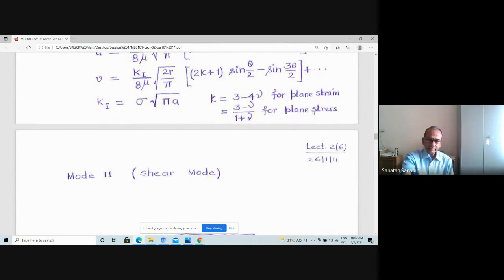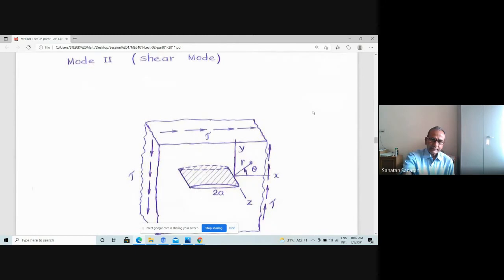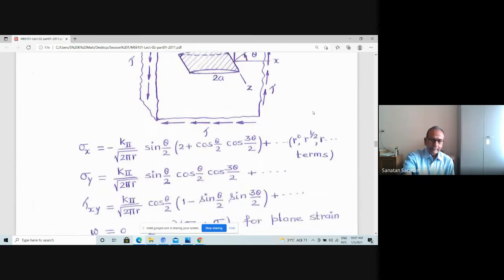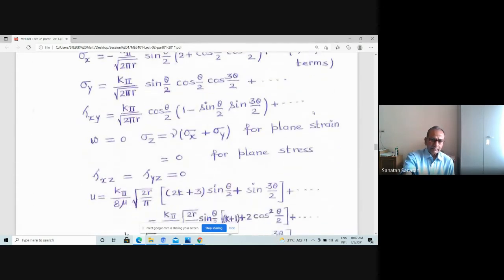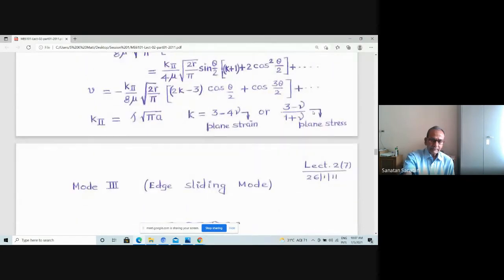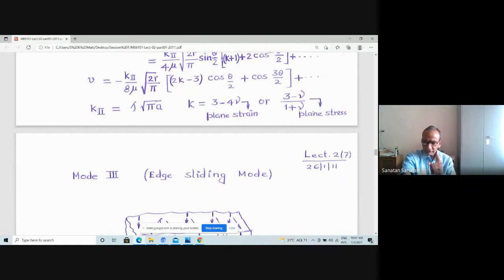Then the loading that he considered, he considered that in practice, the loading can be in 3 fundamental modes. First one is opening mode, where the loading is acting perpendicular to the crack plane. Then he considered a second way of loading, where it could be parallel to the crack. You see, this is actually shear mode loading. Loading is parallel to the crack plane, so it is considered shear mode. And again, he analyzed the stresses and displacements and gave the value of this parameter K2. So these two modes are there.